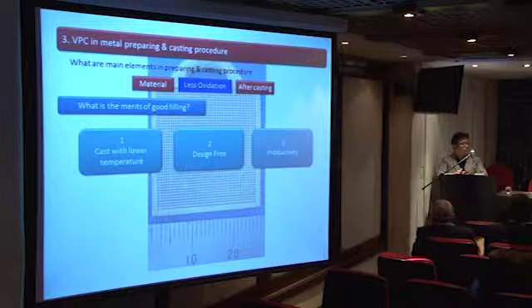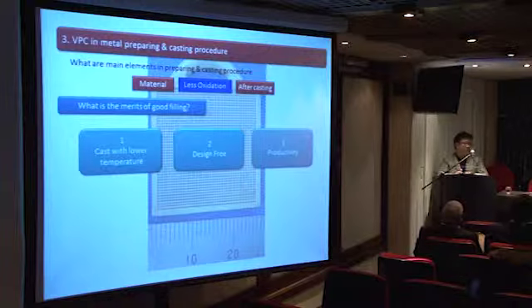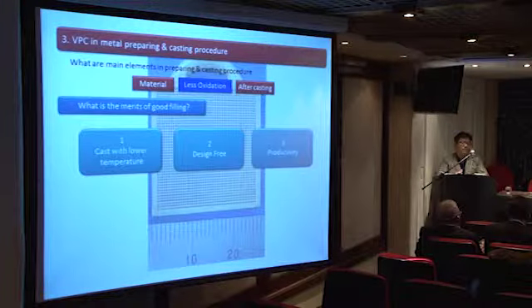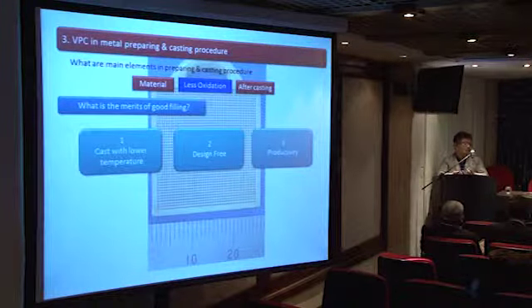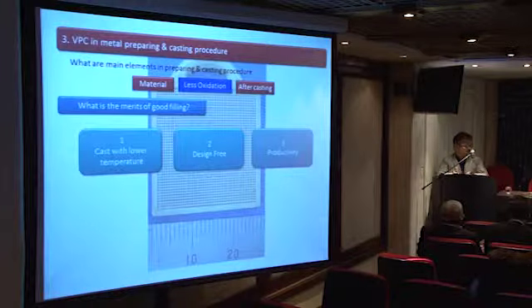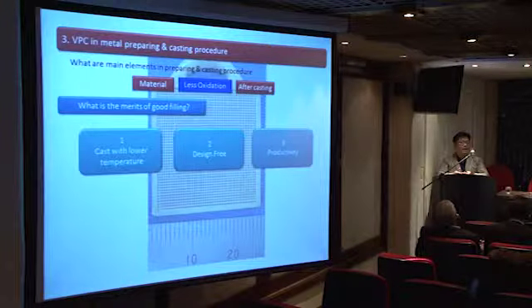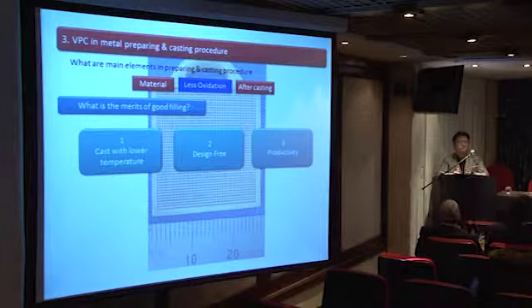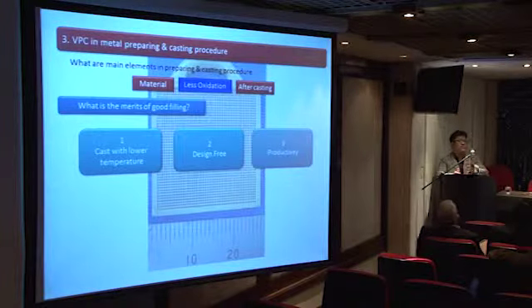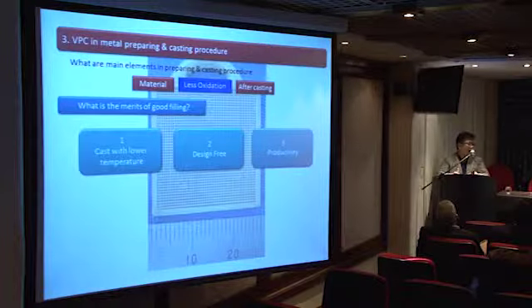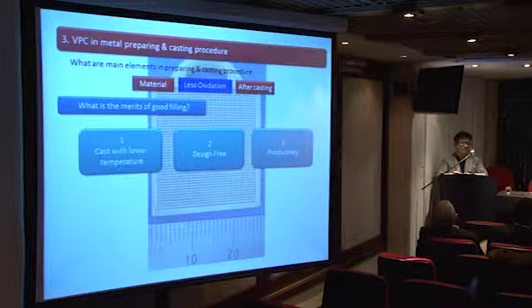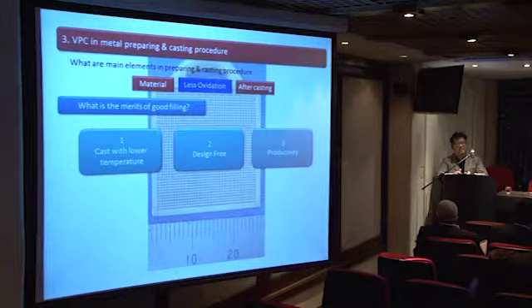If I'm able to reduce the time of polishing, that means I'm not losing a lot of the designs. Polishing means I'm losing metal. Not only the time, but the more I polish, the more metal I lose. Losing metal means we're losing designs, we're losing the shape of the designs. In order to keep the designs, especially on the filigree, you need a smooth surface so that we don't have to polish a lot. In order to do that, the only way is to take care of your metal.